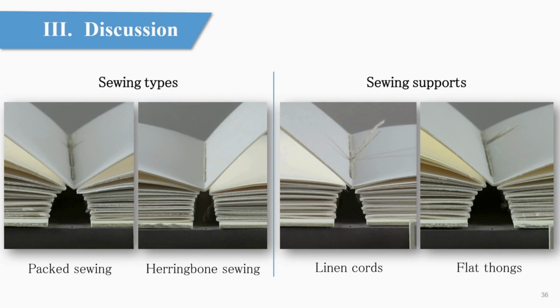Herringbone sewing is still an interesting option, however, if the text block needs to be held more firmly and compactly. A comparison of the results of the mechanical fatigue test, the spine curvature measurement, and the photography protocol shows a clear correlation between the shape of the spine arc and the mechanical fatigue strain. If the arc is wider and more uniform, the sewing supports are better protected. The opening and closing of the book primarily affect the sewing supports, which are exposed to repeated compression.